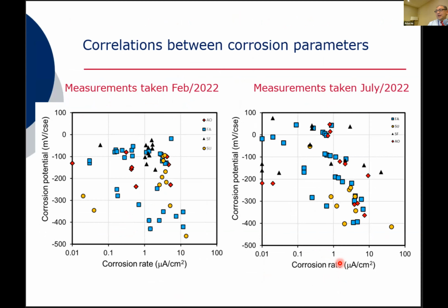As I was mentioning, we used the HECOR during 2022. And here I'm showing you the relationship between the corrosion potential and the corrosion rate. On the one on the left, we have some samples that were later terminated that are no longer included in the picture on the right. But you can see that there is kind of a trend, as is expected: as the potential decreases, the corrosion rate increases, but it's not perfect.